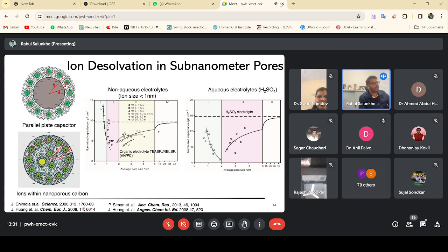Some breakthrough research has been done by scientists and reported in Science, and there are also simulation studies, molecular dynamics and DFT studies, reported. They found that if the pore size decreases below 2 nanometer, then the supercapacitor performance increases abruptly. Whereas as we go on increasing the pore size, the performance stabilizes at a certain value, while below this we get a very abrupt increase in the capacitance. That means that ion desolvation into sub-nanometer pores is very essential for improving supercapacitor performance.